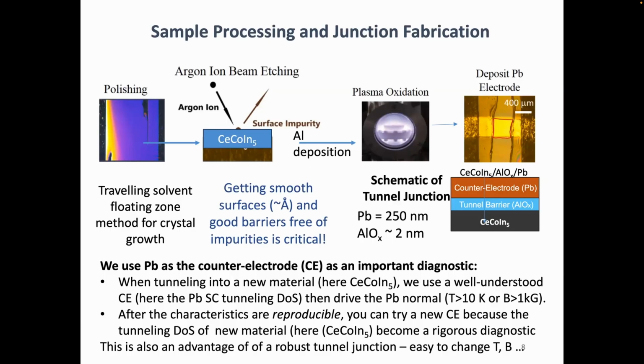Now, what I want to stress is, why do we use lead as a counter electrode? We use lead as a counter electrode because we're not sure what the tunneling density of states of the cerium cobalt indium-5 is. Therefore, if we go down to low temperature with zero applied field, we know exactly what lead planar tunneling density of states looks like. And so that becomes a diagnostic for the quality of the junction. After you do this a bunch of times, and then you drive the lead normal. I'll show you the next one.